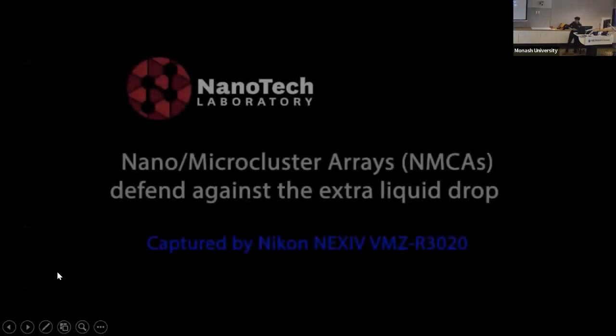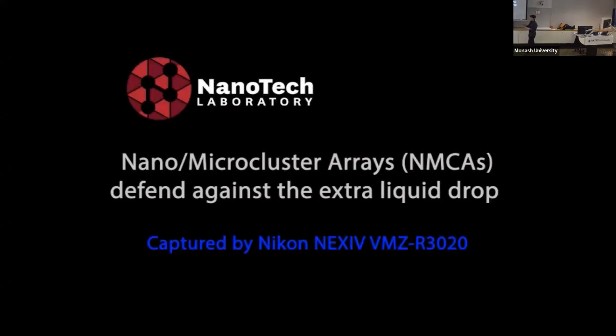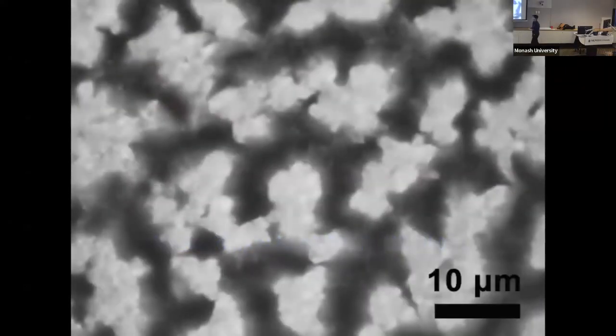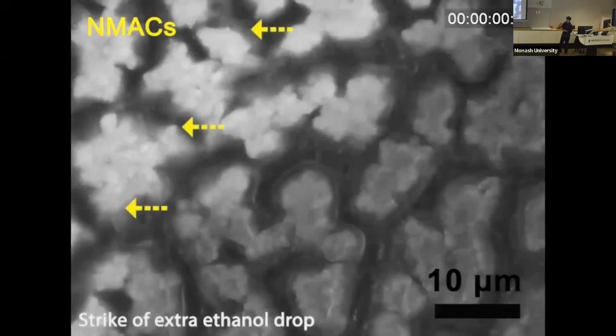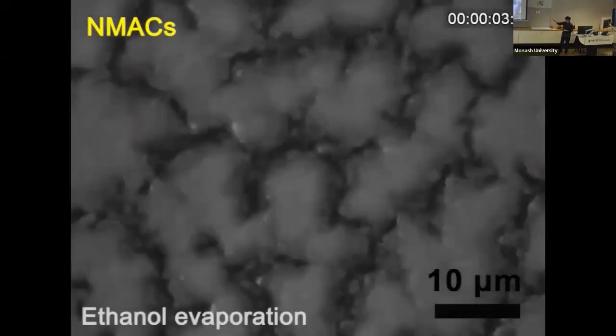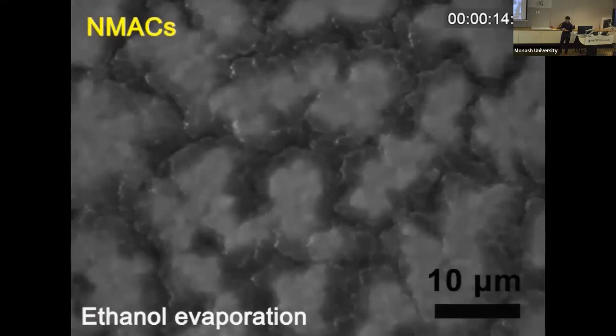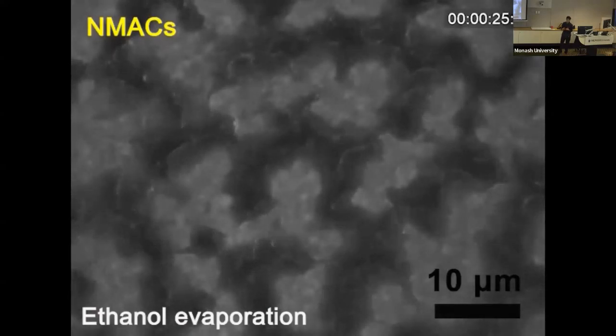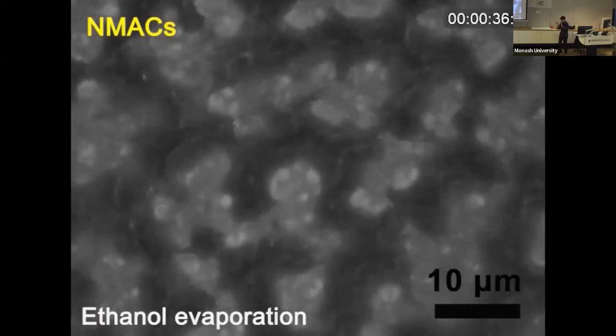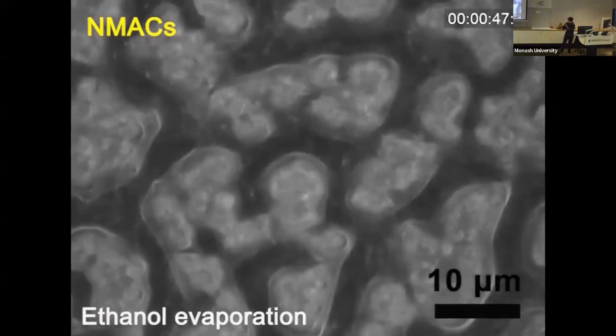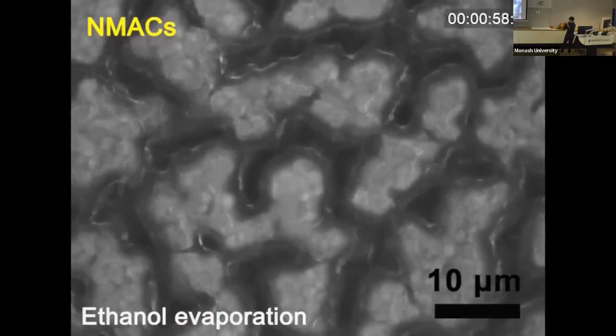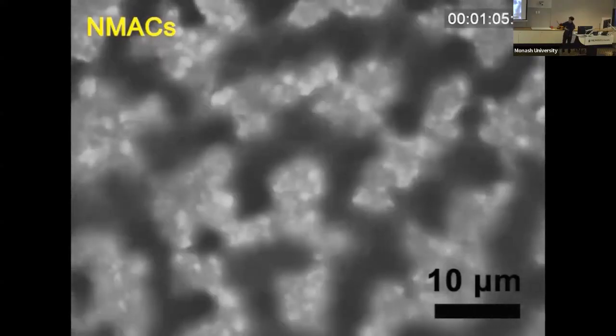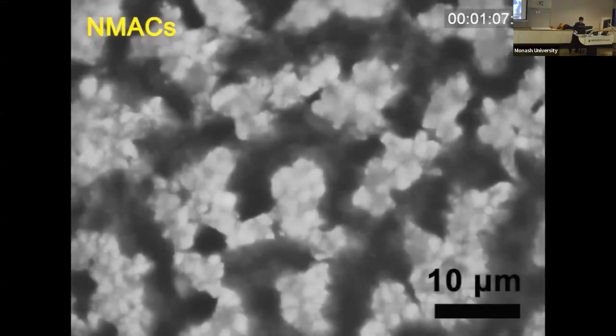The other property that this film is giving us is that now the film is very strong. If I add another droplet, a much larger droplet, to this structure, it's not going to change anything anymore. So now you can dip this film into the water, you can leave it in the water, and it's not going to be damaged by any liquid anymore, because the first droplet, which is perfectly designed in terms of size and evaporation rate, creates such a stable structure that the second droplet is not really damaging the film anymore.